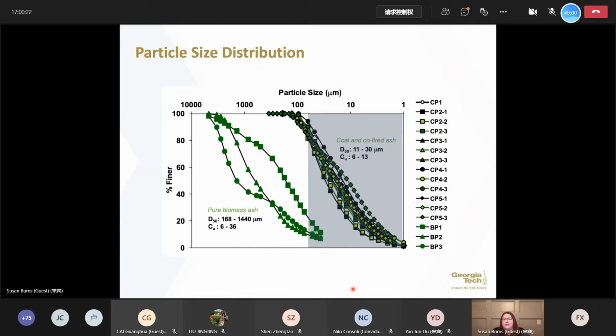In terms of geotechnical properties, when we look at the particle size distribution, our coal ashes and our co-fired ashes come here, and they'll classify in the USCS system as a silt. Most of the biomass plants that we have dealt with are actually not full-scale power plants. And what you'll see as a result of that is that we get a much larger grain size distribution. You can see these in green here are ashes that were produced by combustion of pure biomass. We have a much larger D50, and you can see here that our uniformity coefficient is larger as well.